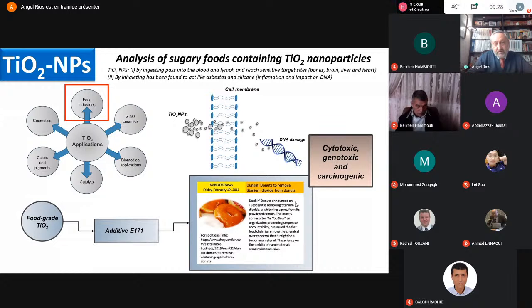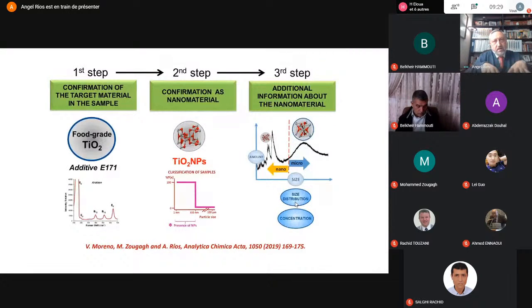And we have developed in this way a screening and confirmation method in order to give information about the presence of titanium dioxide nanoparticles in food samples. It involves three main steps. The first one is the confirmation of the target material, in this case titanium dioxide, in the sample. The second step is the confirmation that the titanium dioxide is in fact present as a nanomaterial, meaning at a size lower than 100 nanometers. And the third step is additional information in order to confirm the presence of this nanomaterial in the sample.